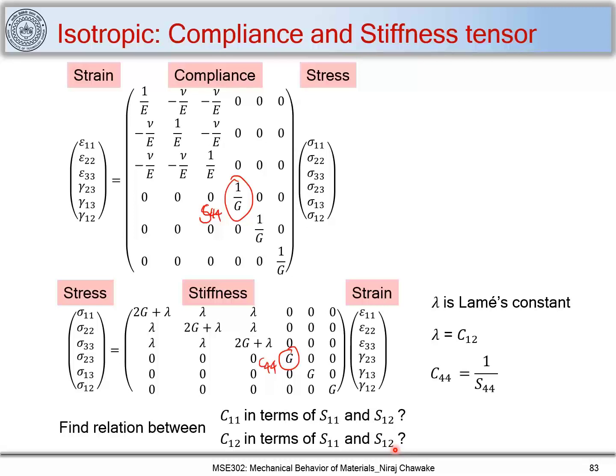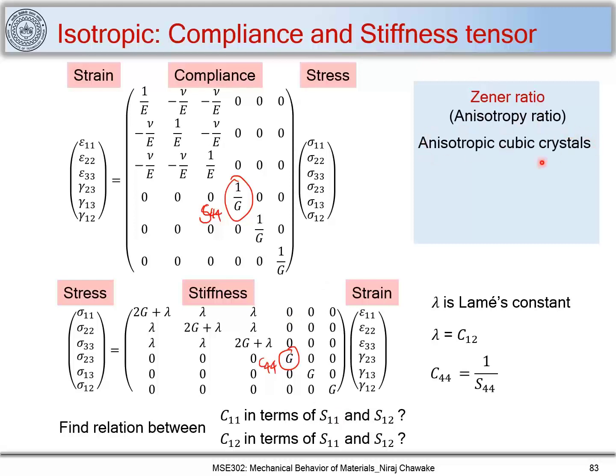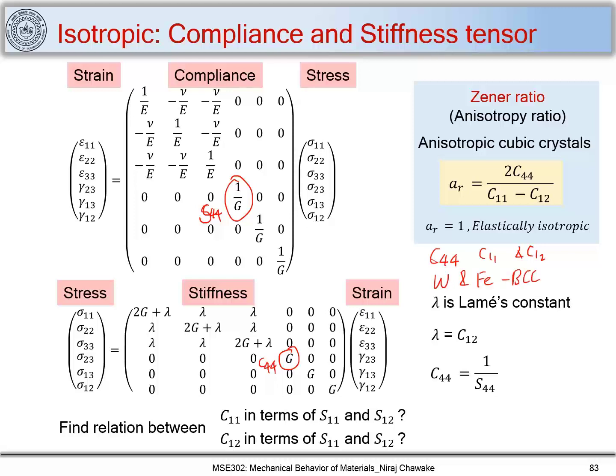I would like to introduce another factor necessary for quantifying anisotropy in cubic crystals — the Zener ratio or anisotropy ratio. It is defined as A_R = 2C₄₄ / (C₁₁ − C₁₂), and applies only to cubic crystals. If this ratio equals 1, the material is elastically isotropic; if it deviates from 1, the material is anisotropic. As an exercise, find C₄₄, C₁₁, and C₁₂ for tungsten and iron (both BCC) and compute A_R.